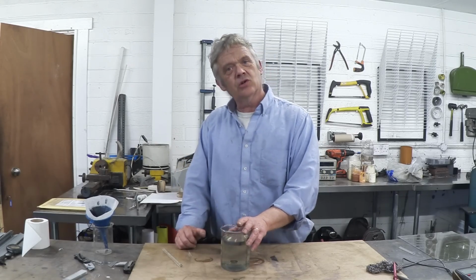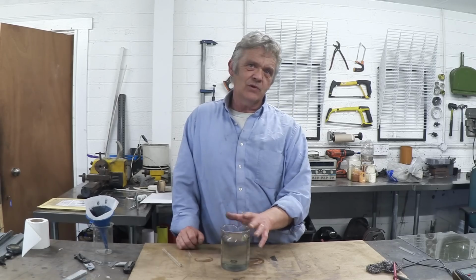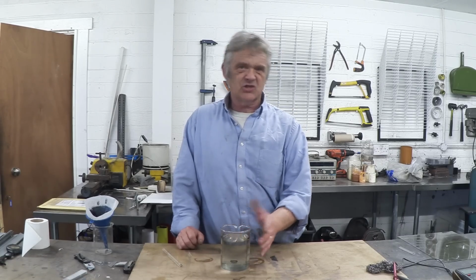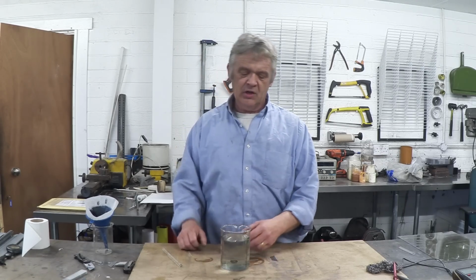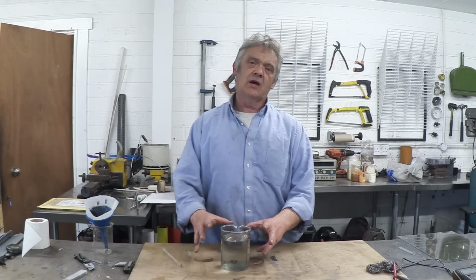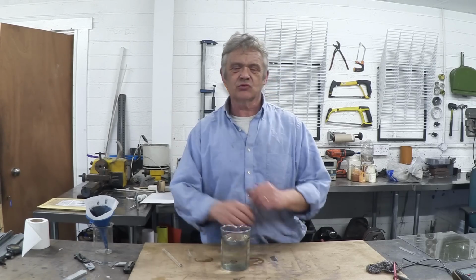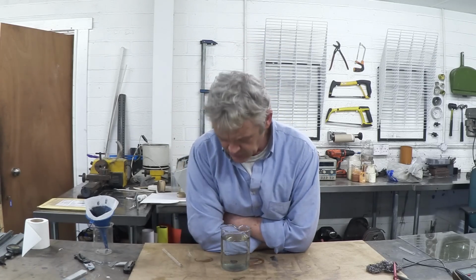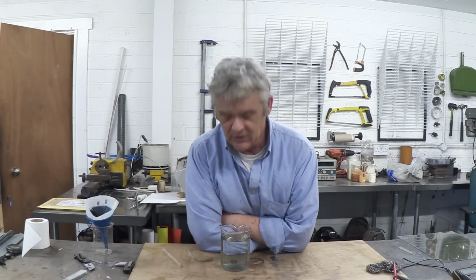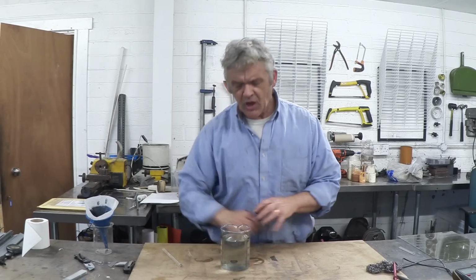Now, what's really cool about using oxalic acid is if we leave this between 2 and 5 days, so 5 days, just set it to one side, any impurities in there are going to precipitate out. And that's just really bizarre. It's not so important here because obviously we just put in resin and indium tin oxide. So pretty much all that's in there is the indium and the tin. But if you crush the glass, you will get some leaching of aluminium and some silicon going in there as well. And you can't stop that.